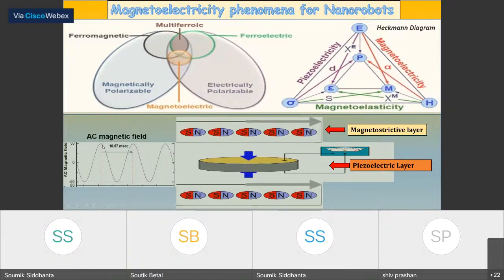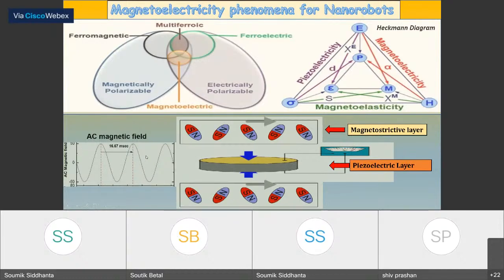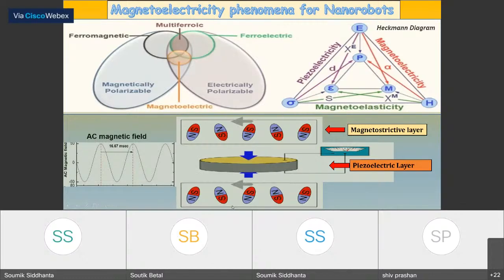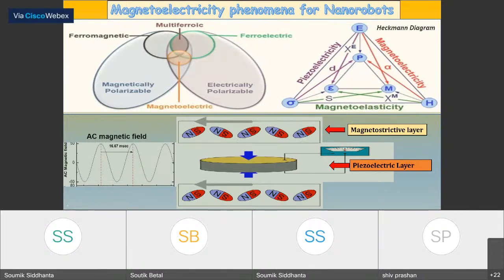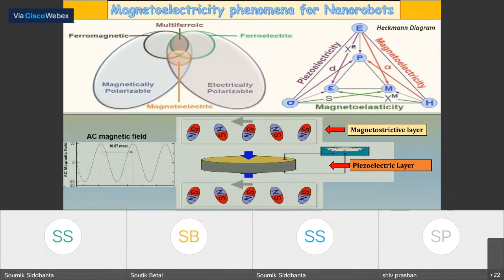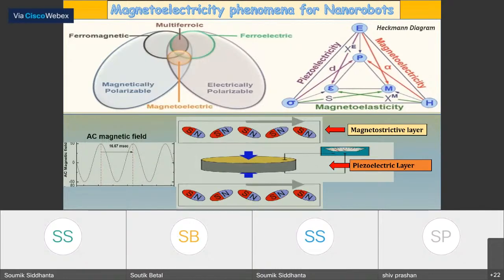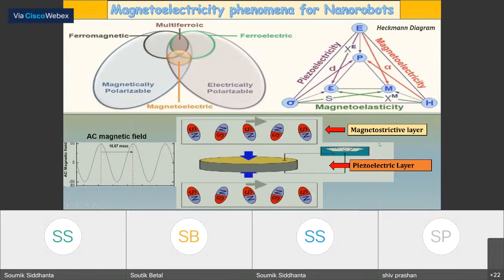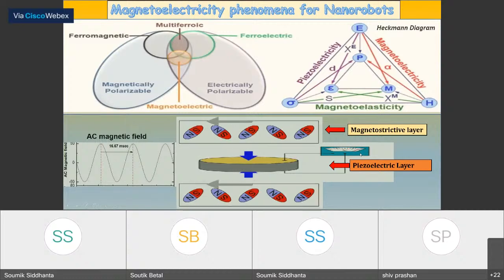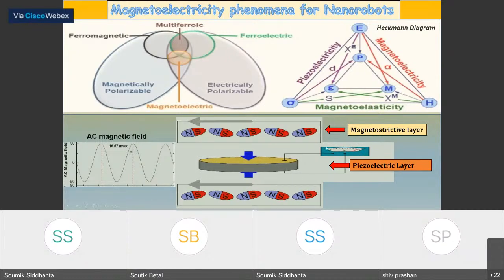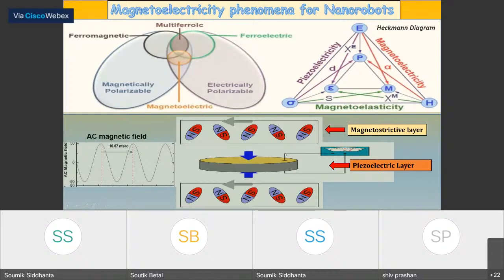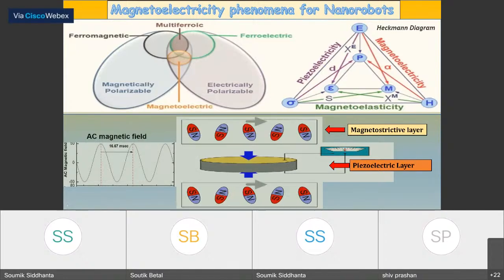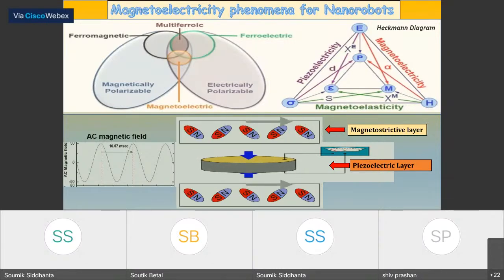When an AC magnetic field excitation stimulus is applied to this device, the two magnetic layers will start expanding and contracting because of the magnetic dipolar reorientation following this magnetic field wave. Now this strain is passed to the middle piezoelectric layer, and it will generate electricity. As you can see, the voltage fluctuations are generated. Interestingly, the amplitude and frequency of this electricity will follow the excitation magnetic field frequencies.